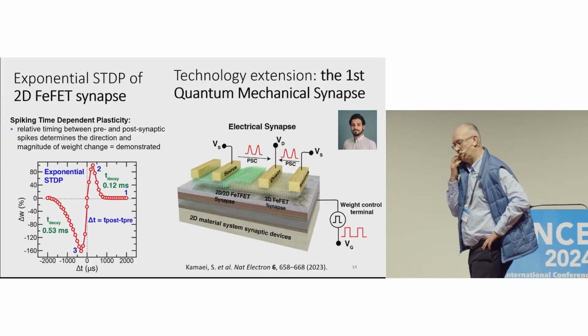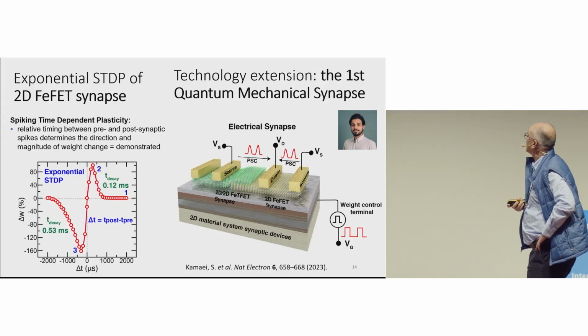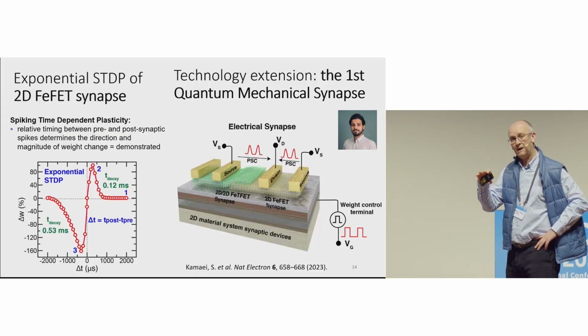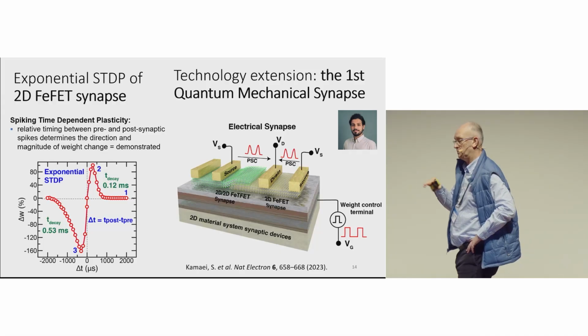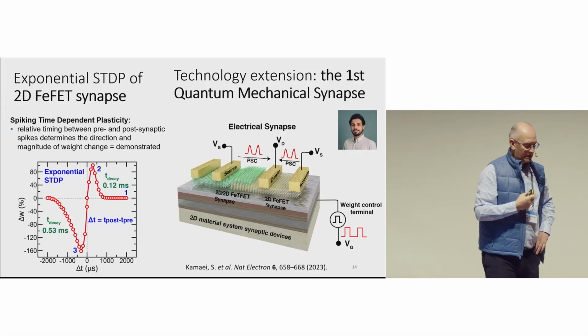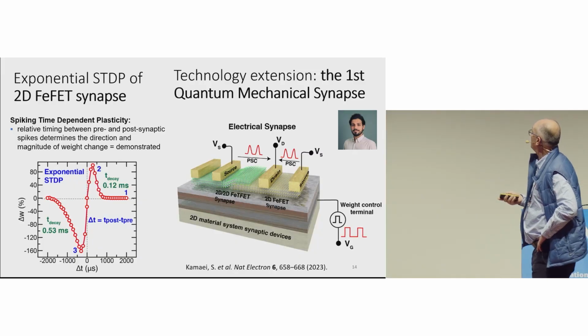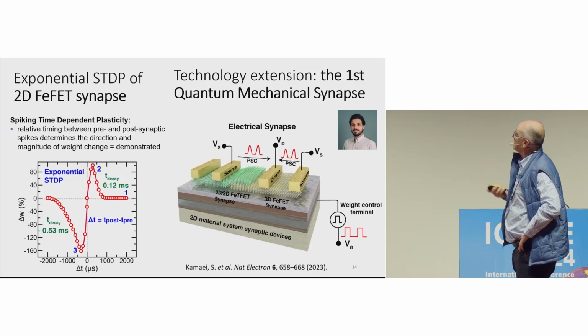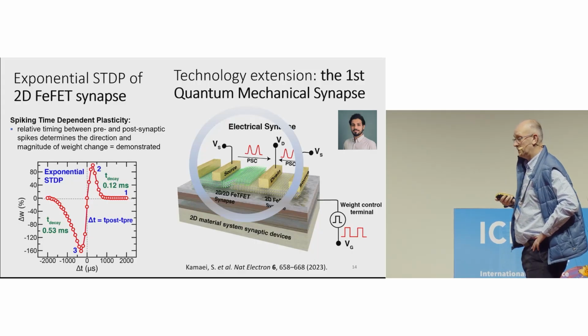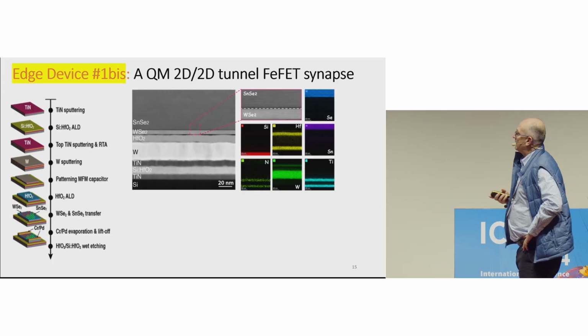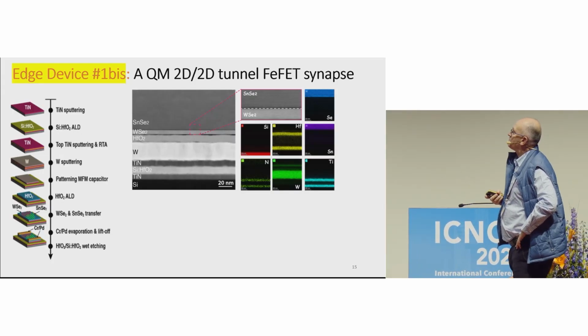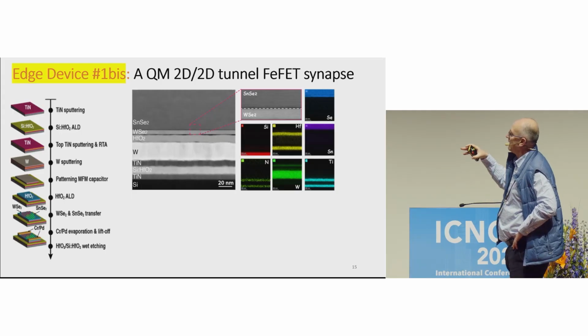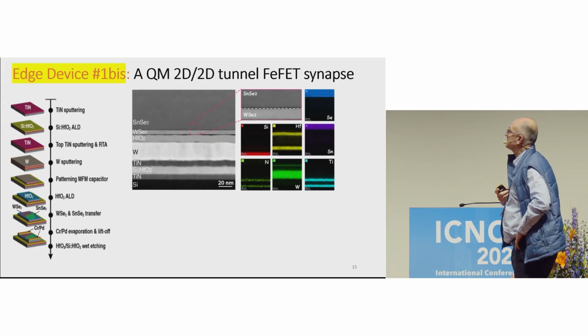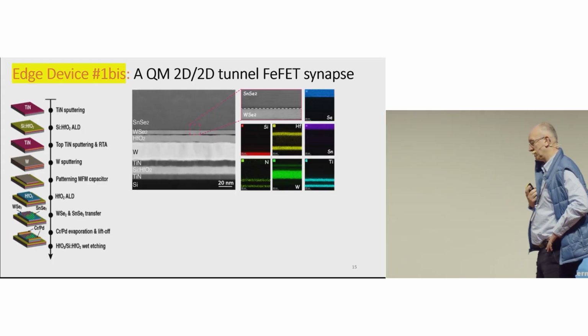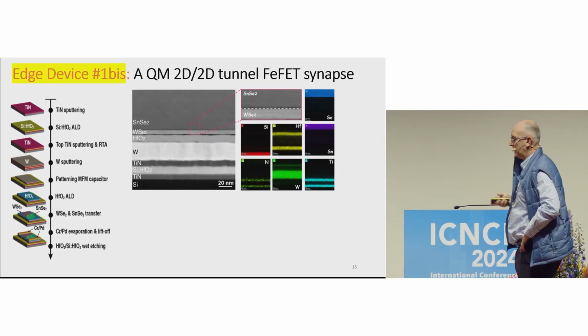The advantage of a van der Waals tunnel FET, 2D to 2D, that here is just schematically represented, is that you do not have much trap-assisted tunneling at the interface, which usually is killing the tunneling FET property. So if you do a good transfer and you build the right alignment of band, you can achieve a very nice tunneling and abrupt characteristic. And we gate it with the ferroelectric, now the 2D to 2D tunneling device. It was a bit more complicated in the fabrication because now we have to use on the same stack a tungsten diselenide, tin diselenide type of heterostructure that for us has the best alignment to obtain band-to-band tunneling.